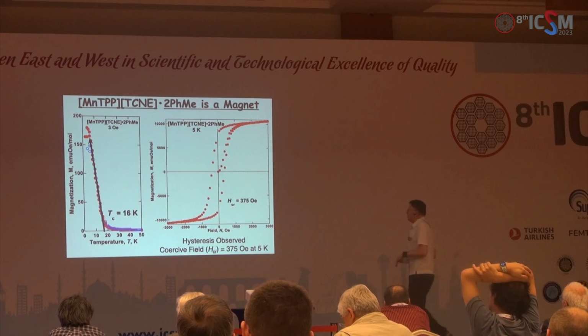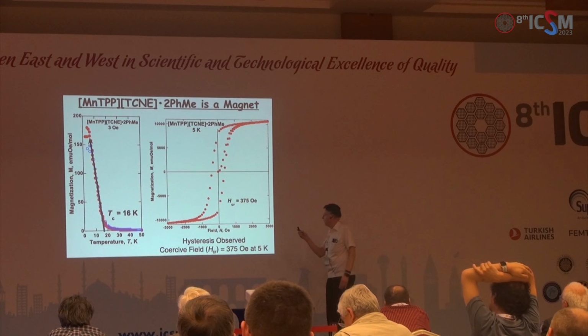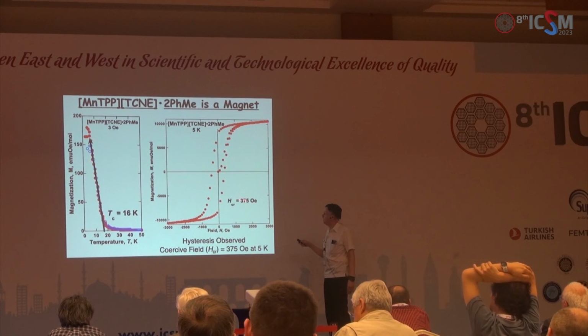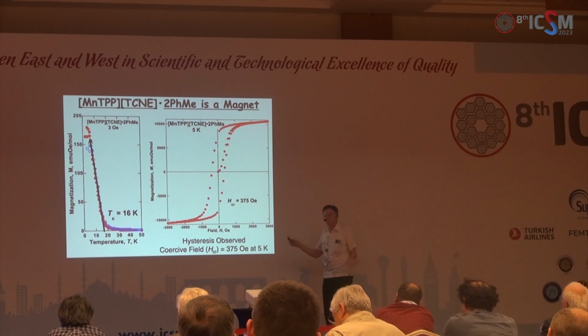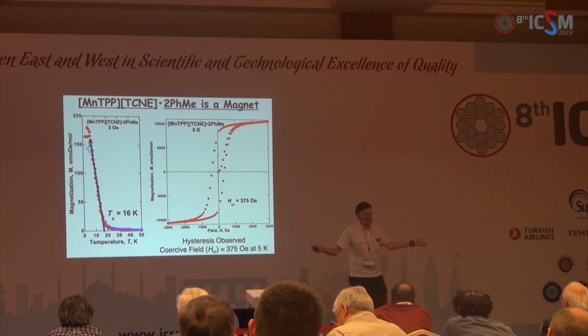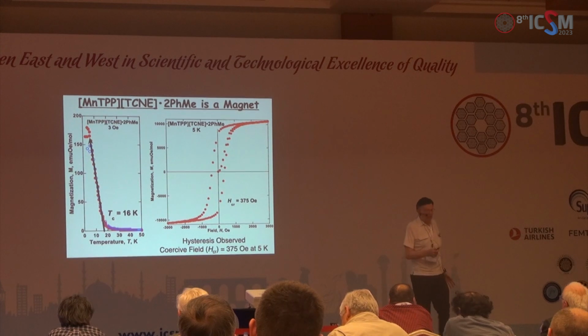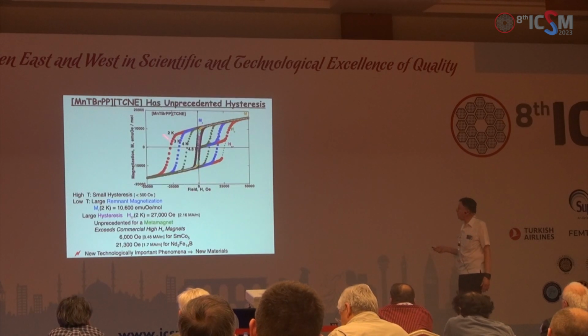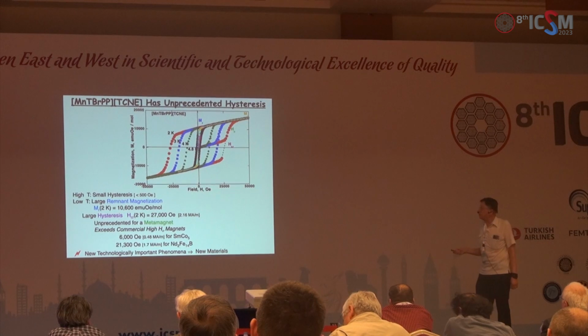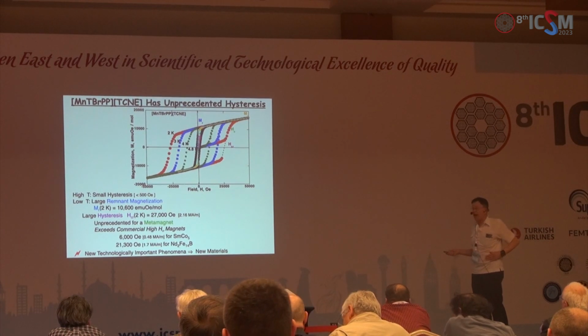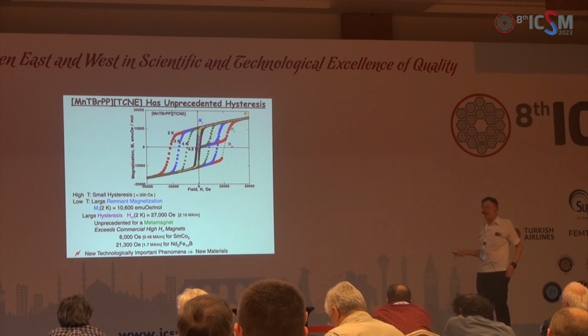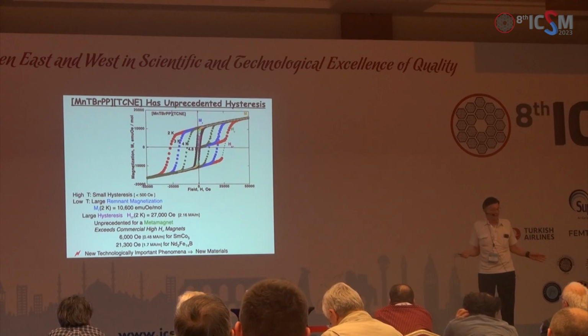Now notice at 5 Kelvin, the hysteresis loop shows a coercive field of 375 Oersteds—a nice textbook hysteresis loop. However, if you cool it down, it goes from 375 to 27,000 Oersteds at 2 Kelvin, reversibly.